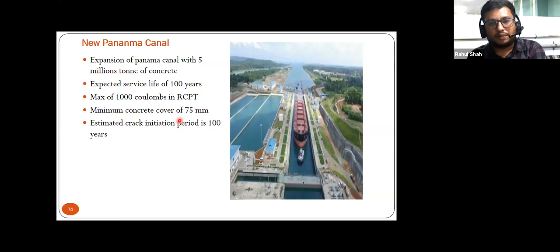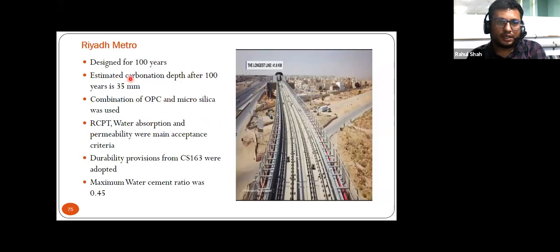So this particular parameter, the initial service life or first crack, is generally as per Tuutti's model, which is very famous in service life prediction, that tells us what the initiation period is and how after that the concrete will behave. Riyadh Metro, it is again designed for 100 years. So this durability is for 100 years. It is not like structural life is for 100 years. And the carbonation depth after 100 years is 35 mm. So you can see their confidence that after 100 years also, this depth is not more than 1.5 inch.